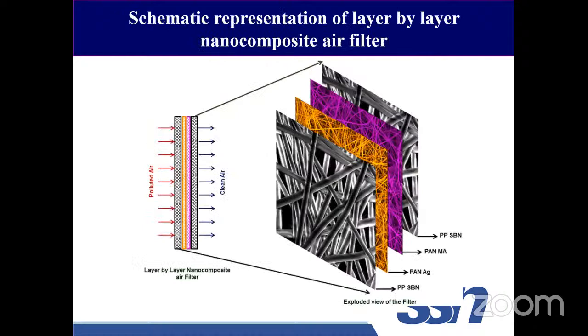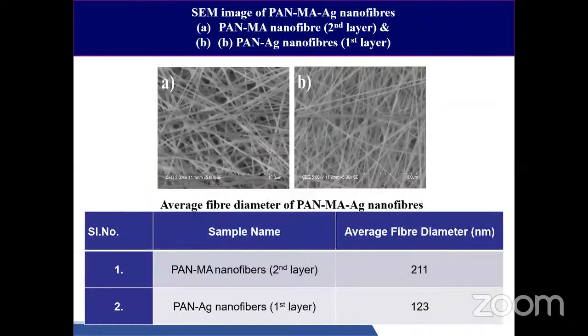So we prepared a triple layer membrane. This is the exploded view of the filter that we developed, where we have the inner surface and the outer surface made of PP spun bonded non-woven. And between the spun bonded non-woven, we have incorporated 2 layers of nanofibers. The first layer is made of polyacrylonitrile with silver incorporated membrane, and the second one is made of polyacrylonitrile with magnesium aluminate. This is the image of the prepared 2 layers. Magnesium aluminate has a fiber diameter of 211 and the silver nanoparticle has a fiber diameter of 123.